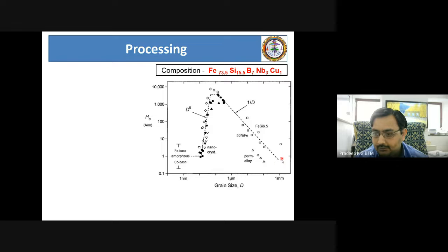That means we need to have a large enough grain size to have a low coercivity, or on the other extreme, we need to have nanometer grain size or much smaller grain size to have the lowest coercivity. The lower the coercivity, the less energy loss there is going to be. That means now you just see here, if you are able to reduce the grain size D within the range of 100 nanometer to possibly 10 nanometer, for each decrease in nanometer, you get a 10⁶ decrease in coercivity.